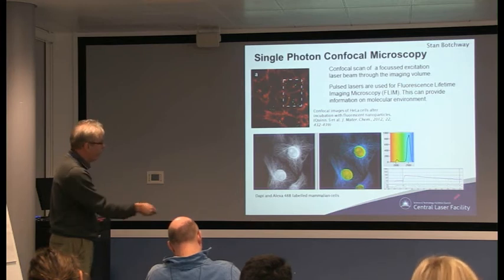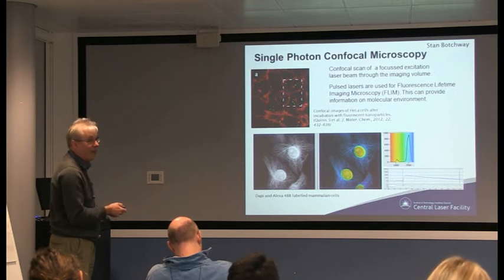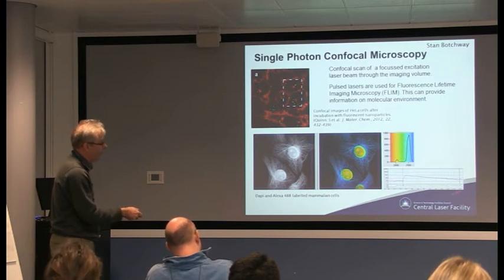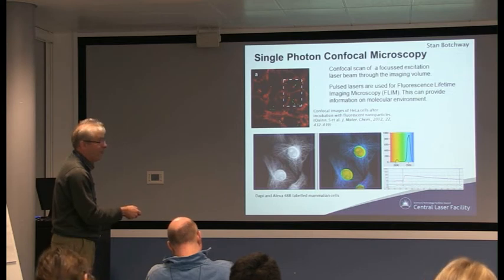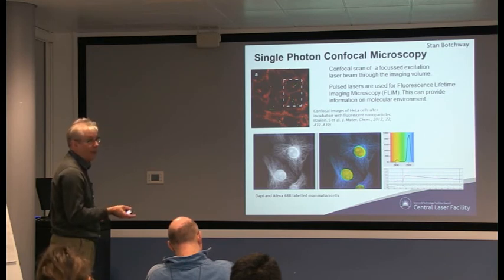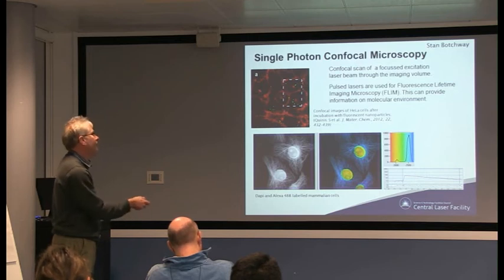If I point you to this plot in the bottom right-hand corner, this is called a fluorescence lifetime image. This is the actual decay of the spectrum with time. The pulse of the laser would come in here somewhere, shortly afterwards you get the fluorescence, the pulse would go off, and you'd watch the fluorescence decay. Typically that goes with either mono-exponential or bi-exponential decay properties, so you get a lifetime of that decay.